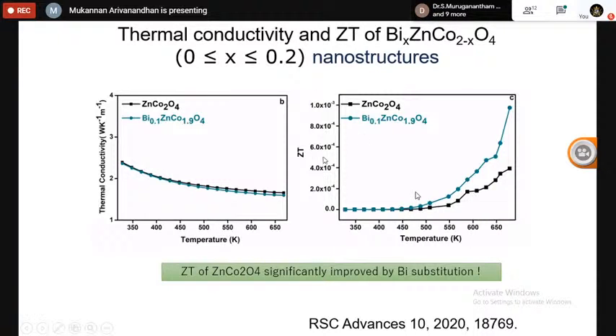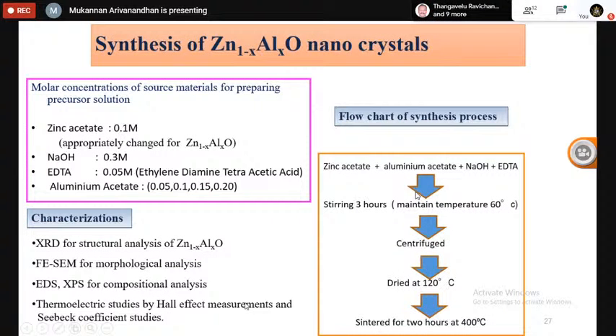So although the ZT is quite low for this oxide material, there is a systematic change observed between the bismuth free as well as bismuth substituted samples. So this shows that the bismuth substitution has some strong influence on enhancing the thermoelectric performance of these zinc cobalt oxide materials. And similarly, we have analyzed the thermoelectric characteristics of zinc oxide.